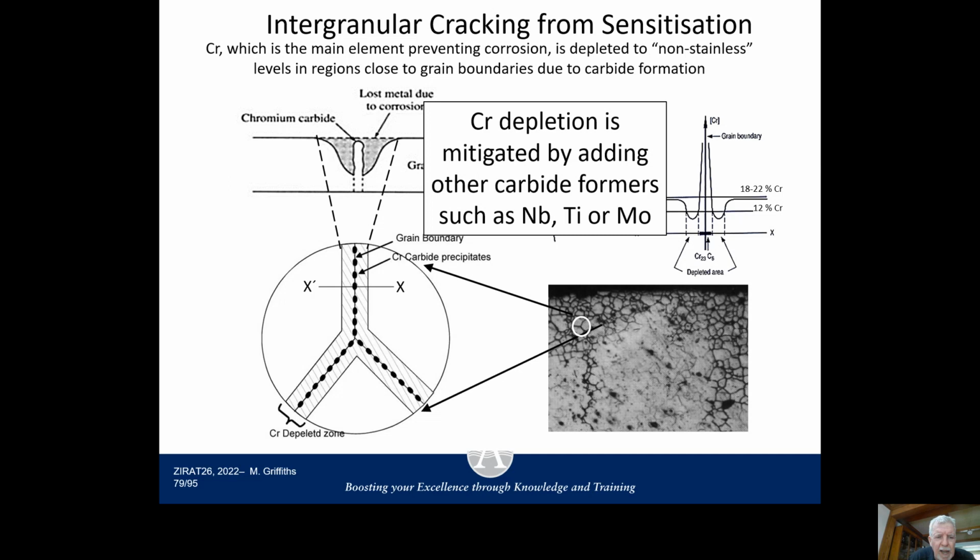When a carbide forms at a grain boundary, I showed you earlier that carbon precipitates on grain boundaries, a carbide former there. And chromium is a strong carbide former. It also is a fast diffuser. So you tend to get chromium being depleted when you get carbide formation at the boundaries. And this leaves you then more susceptible both to corrosion and intergranular attack by various species.